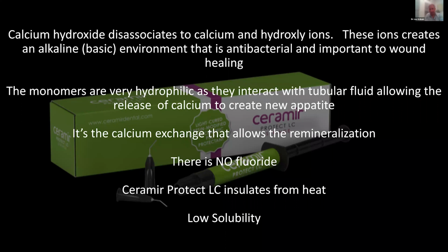Now, because the monomers are hydrophilic, you want to leave the dentin mildly moist. So after you remove the decay and you've done your thing with your Cereburs, you'll rinse the area off, blot dry it, don't air dry it, and leave it just minor moist. Then this will flow. There's no fluoride in this, and you don't want fluoride by the pulp, not at all. And these products are all low in solubility.